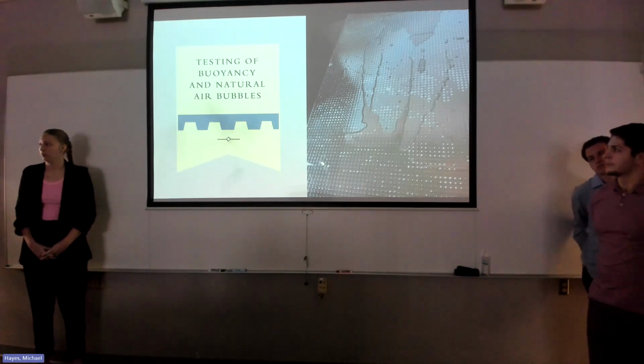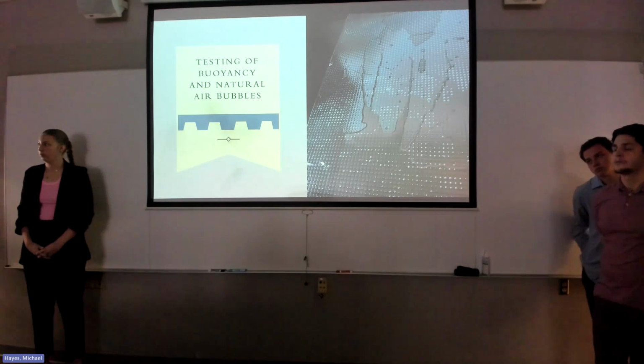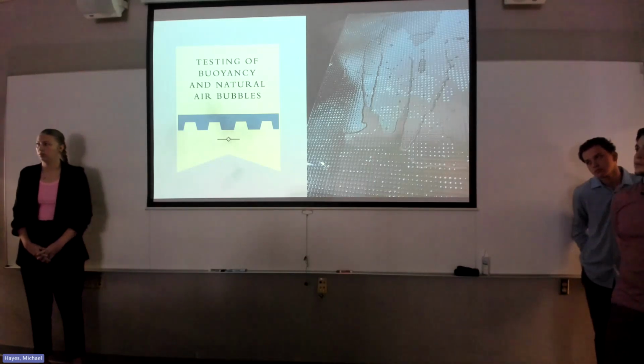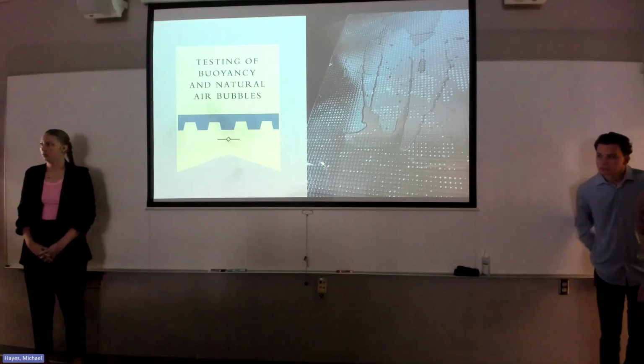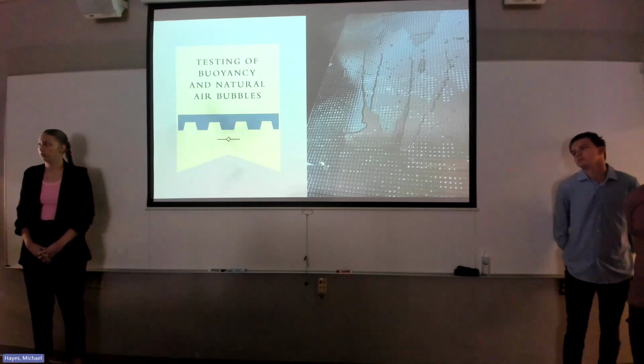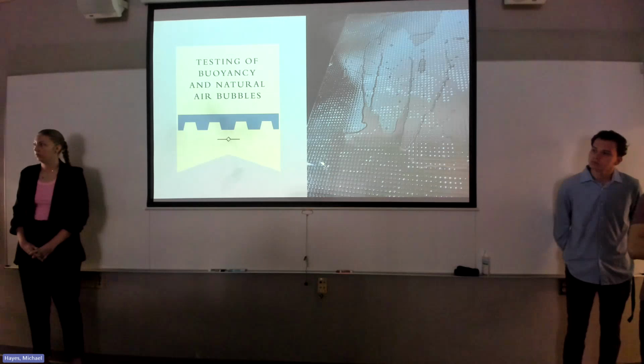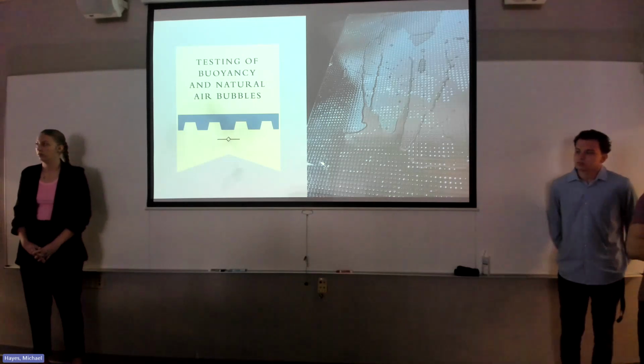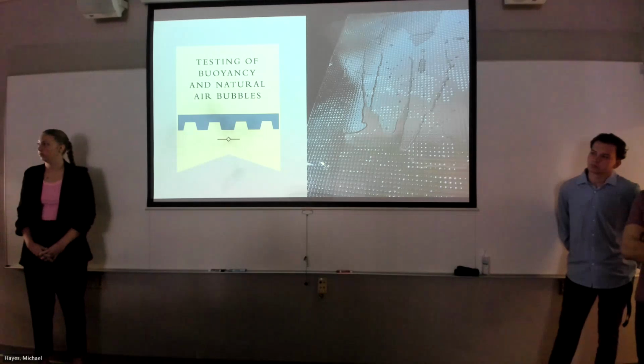Moving forward in the next semester, we have plans to do validation testing with high density polyethylene. One test uses the psychrometric chamber to simulate the dry bulb temperature and relative humidity, plus a purchased UV light, similar to the lights used in tanning beds, to radiate the energy. Then we test the pool temperature over time and look at the mass loss between our high density polyethylene cover and the bubble cover, to see if the bubble is crucial to the thermal properties. We're also going to do a secondary test, which is a manufacturing study looking at different thicknesses of polyethylene covers.